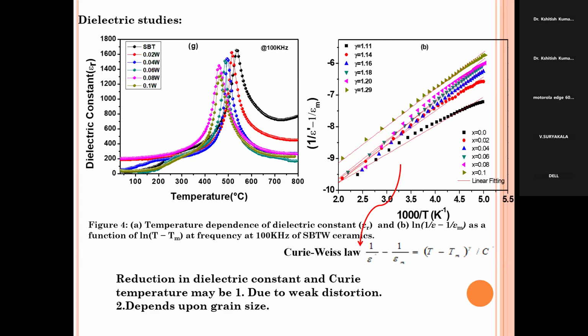Diffusivity means, this is the calculation from the dielectric, we have calculated diffusivity. The diffusivity gradually increases, and that is 1.11 for the parent one, the SBT, and it gradually increases. So one of the advantages we got is that the diffusivity increases. Why does diffusivity increase? We thought that maybe the tungsten is present on the titanium site. For that reason maybe the diffusivity increases, and this increase means the material may be a relaxor material.